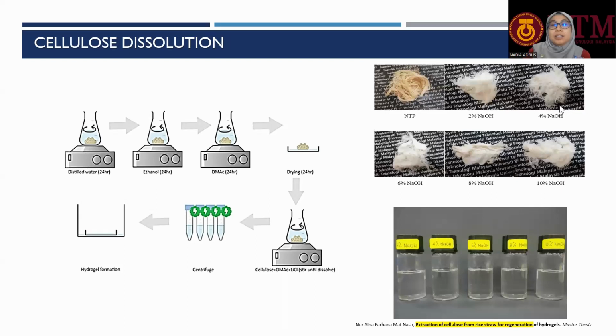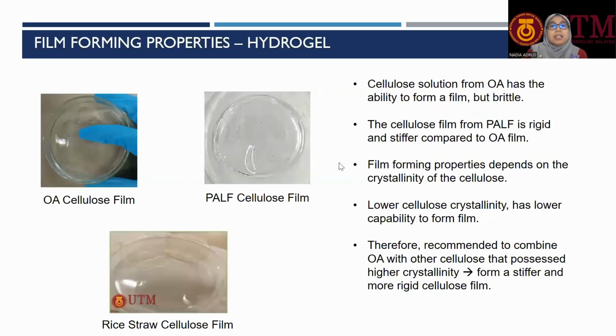So here are the pineapple leaf fibers, treated with different amounts of sodium hydroxide. And here are the physical observations of the cellulose after being dissolved in this DMAc/lithium chloride solvent. And in this slide, I would like to show you that after the cellulose has been dissolved in that solvent, it is also capable of forming film.